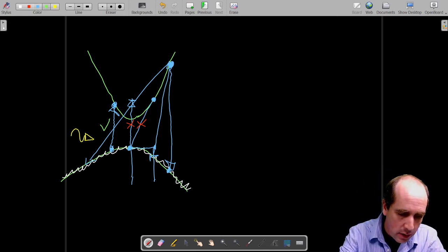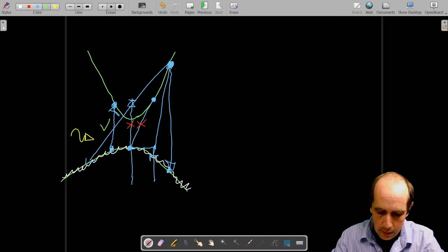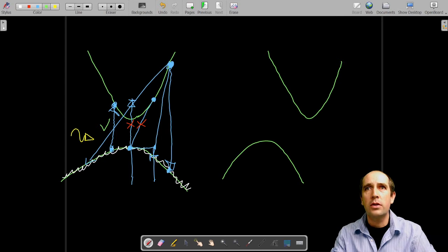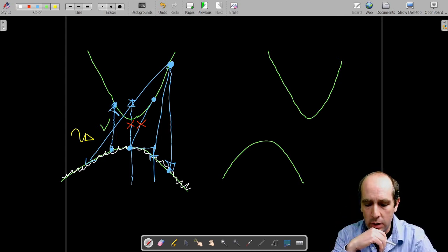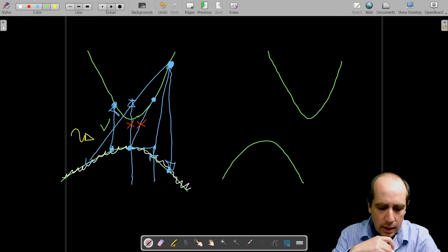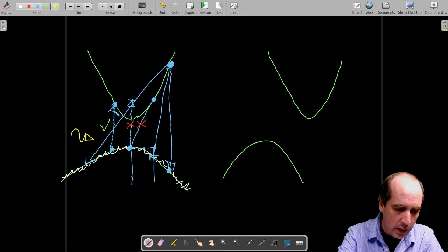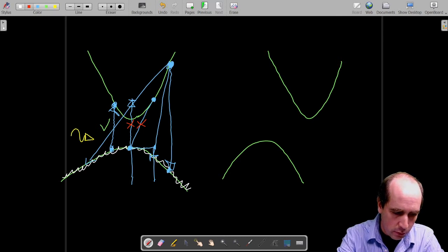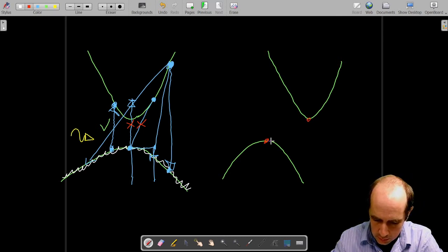Right, so now let's think of a band structure that is not aligned. So here I will draw another band structure in which the minimum of the conduction band and the maximum of the valence band are not aligned with each other. And the question is, what will happen in this case? Well, for the same arguments that we gave, a transition from, let's say, this point to this point is not allowed. Okay, this cannot happen. We know that transitions have to be vertical, so optically mediated transitions.